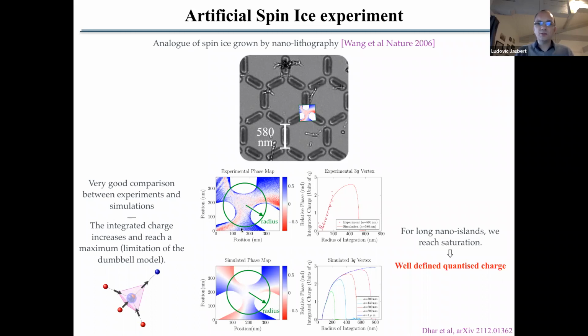You can integrate around the contour of this phase to obtain the magnetic charge. Here again, experiment and simulation match very well. And you can see that in the proper regime, you can get a finite value of the magnetic charge at this 3Q vertex, which means that you can measure an effective magnetic charge in artificial spin ice, and you can see it here. So this is essentially the vector potential of this magnetic charge that you can see here.